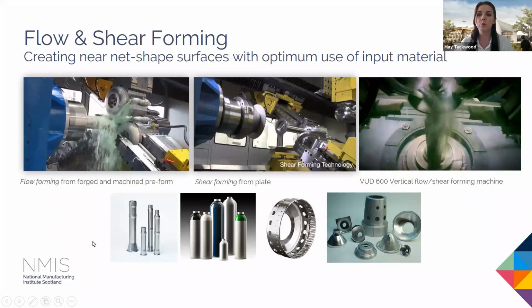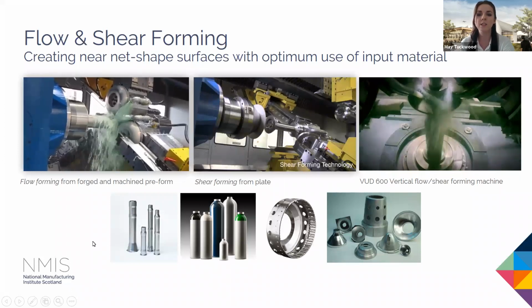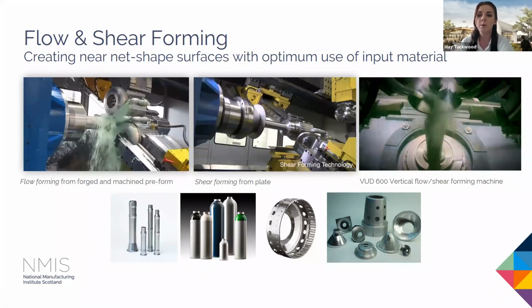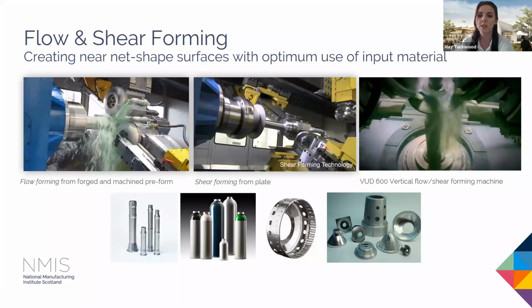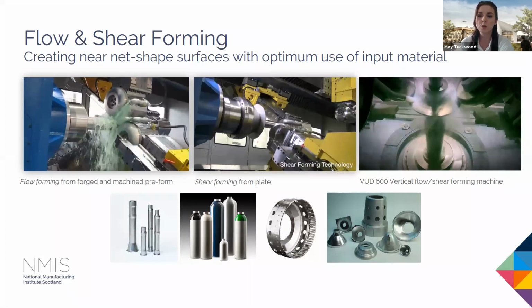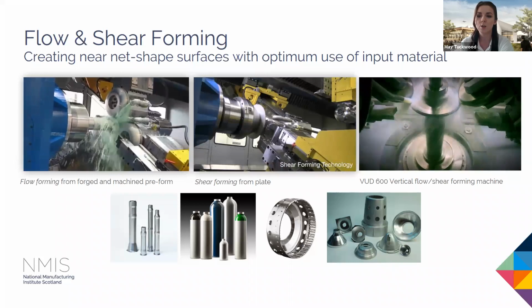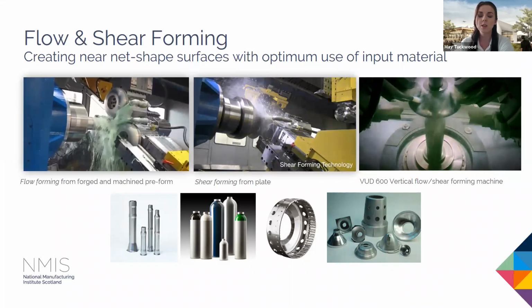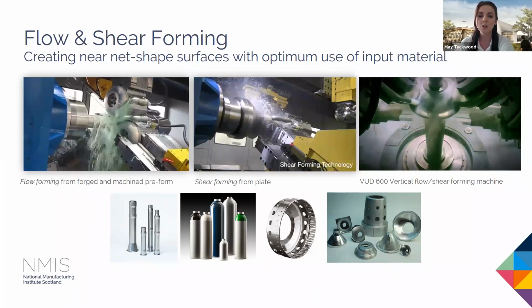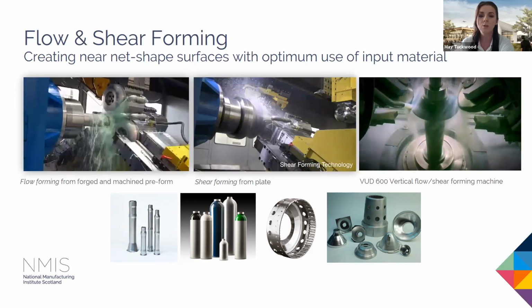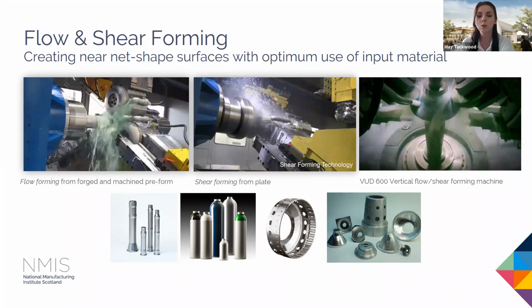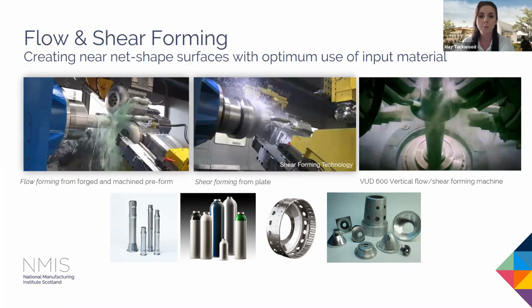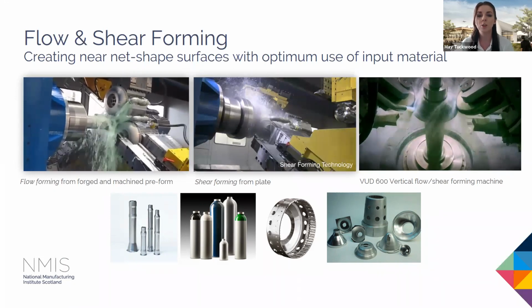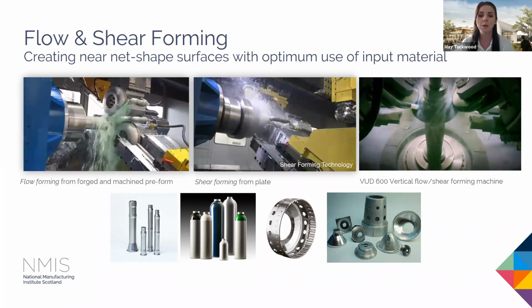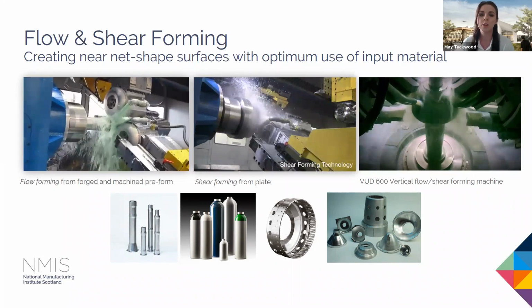So starting off with flow and shear forming, and just to give you an overview of these technologies. So we've got 2 primary pieces of equipment within the AFRC. We've got a large horizontal flow former, an STR 600, which has 3 rollers and 50-ton capacity each. We've also got a smaller machine, our VUD 600, which has a lower load capacity at 30 tons per roller, but does give us greater variability in terms of the complexity of the components.